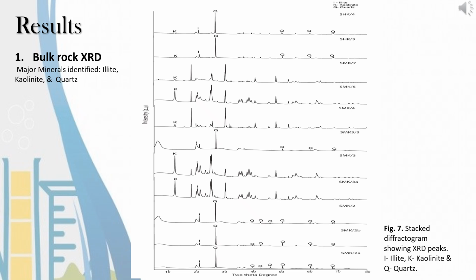Powdered carbonaceous shale samples of size approximately 64 micrometers were analyzed using X-ray diffractogram with a copper K-alpha radiation source at 2 theta angles. The 2 theta angle range taken was 5 degrees to 80 degrees. The result obtained shows a stacked diffractogram in figure 7 with some prominent peaks that correspond to particular mineral phases, mostly illite, kaolinite, and quartz.